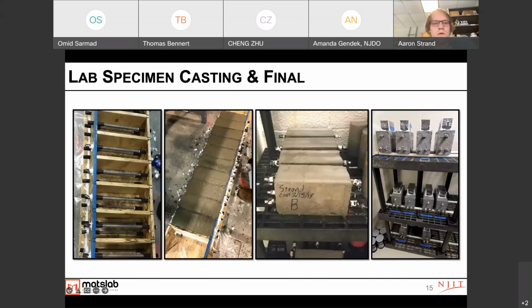So this is what our specimens look like. On the left, you can see what our reinforcement and molds look like, and then when they're all cast. In the center right image is what they look like inside our wet curing room. And then on the right is what the finalized specimens look like, with the plastic dams on top for the ponding of the solution.